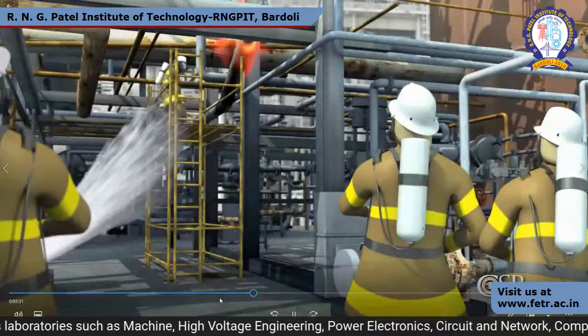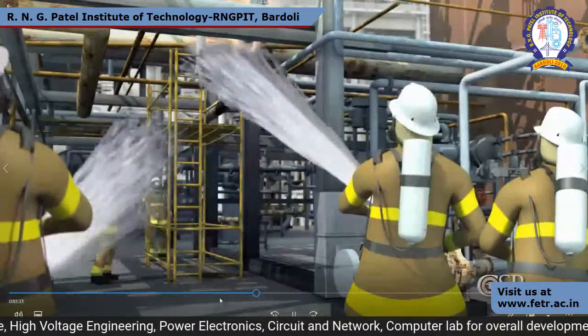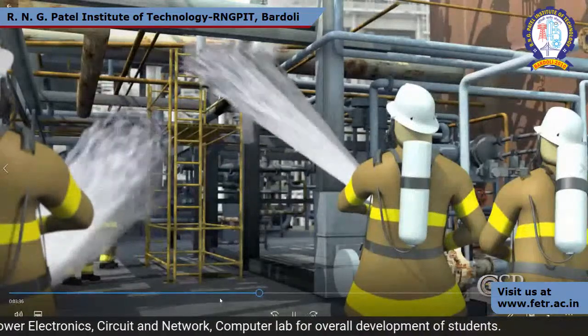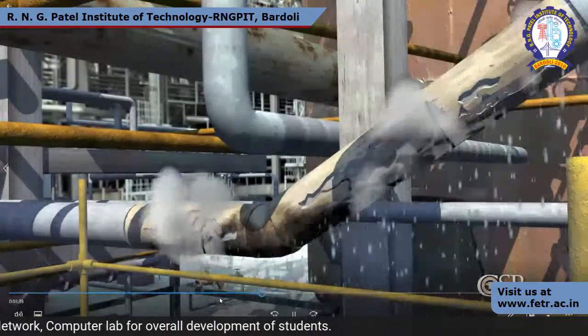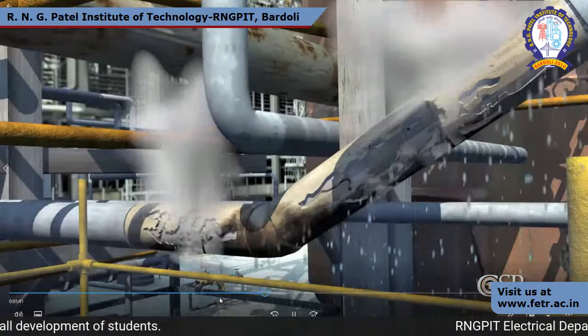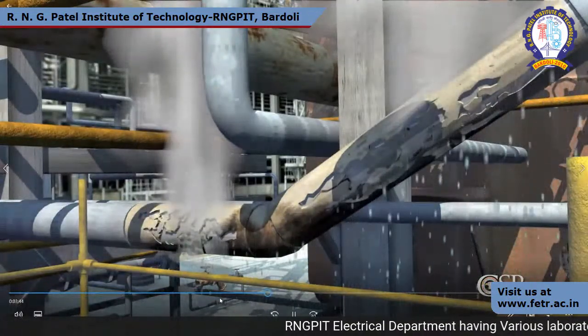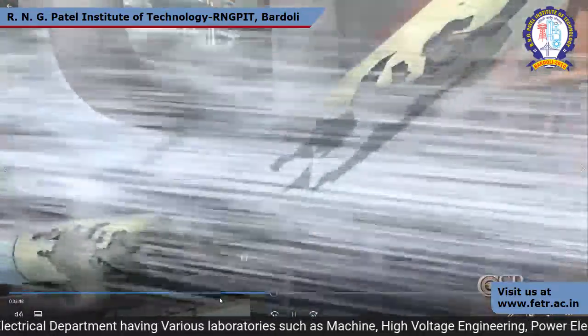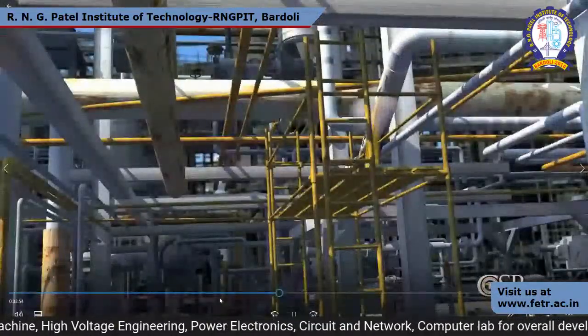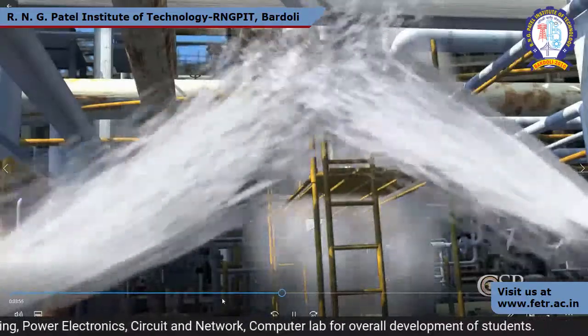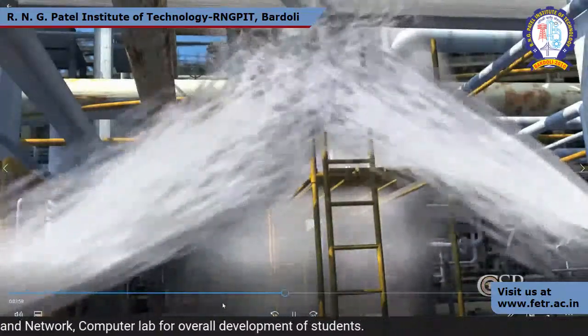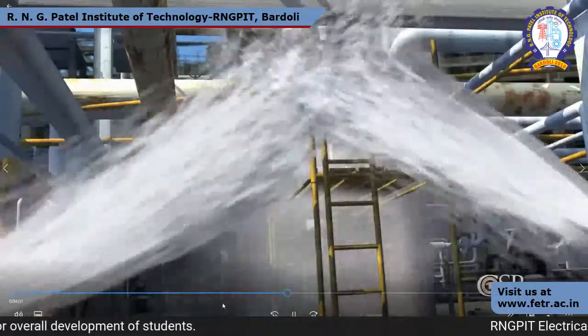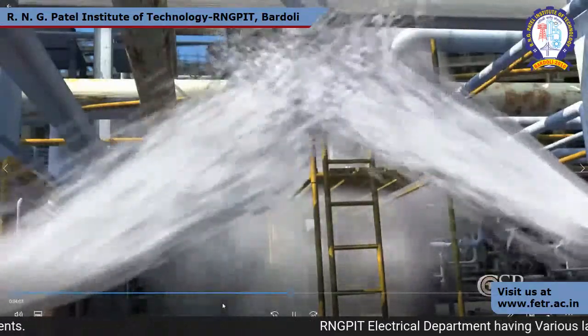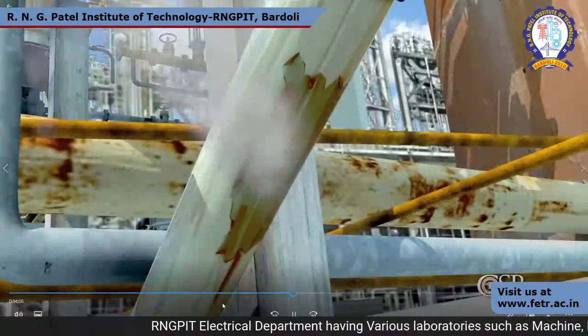That fire was quickly put out, and the two firefighters immediately climbed down off the scaffolding. But the exact location of the leak was still obscured by the remaining insulation and firefighting water. So the Chevron firefighters attempted to strip the insulation off the pipe with high-pressure water. But the leak suddenly worsened, and hot hydrocarbon liquid started to spray out of the pipe. A decision was finally made to begin an emergency shutdown of the crude unit. But it was too late. Suddenly, the pipe ripped open.